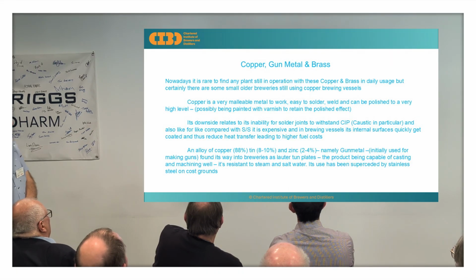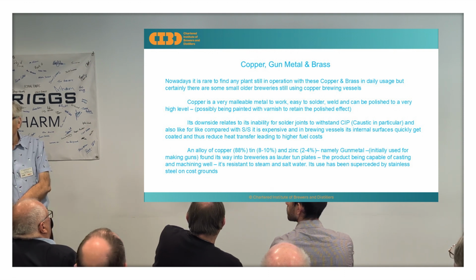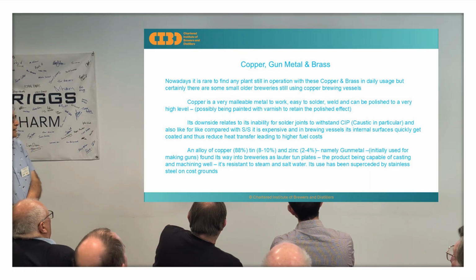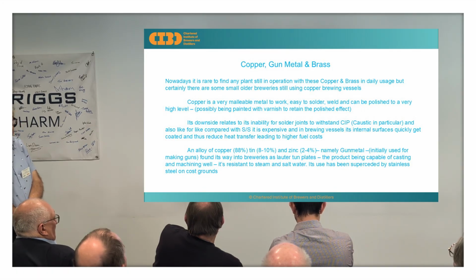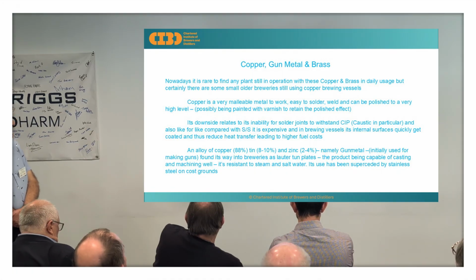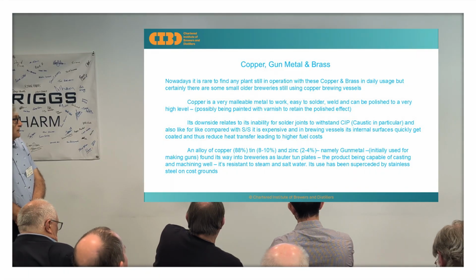Moving on to copper and brass. You don't find many operations still using copper and brass in daily usage. Copper is a smashing material, as I'm sure McMillans would agree, to work with. It's so malleable, you can weld it, and you can polish it to a very high degree, probably varnish it to retain that polished effect. One of the main downsides was the inability of the solder joints to withstand CIPs, the automatic CIPs, and, like for like comparison, it's quite expensive.